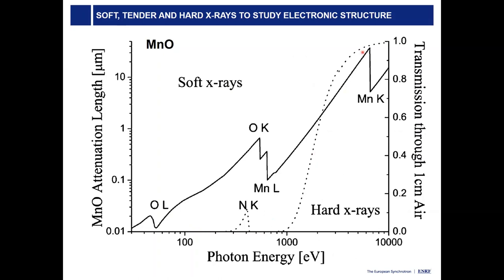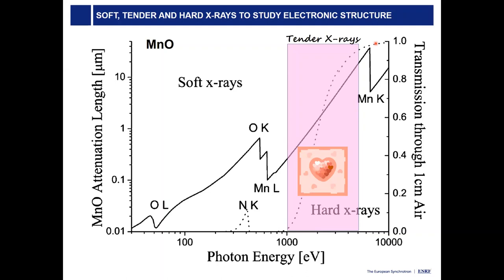And then if you go in the hard X-ray range, it goes to around 10 microns. Here on the right, you see the transmission through air. That's the dotted line there. So through air, 1 centimeter of air doesn't really let much of soft X-rays through, but in the hard X-ray range, I can leave my sample in a gas environment, no problems.